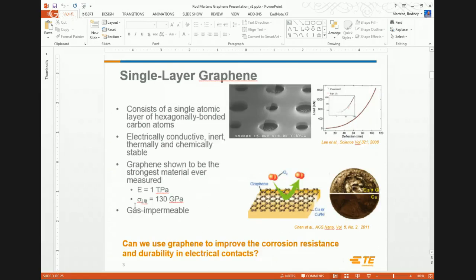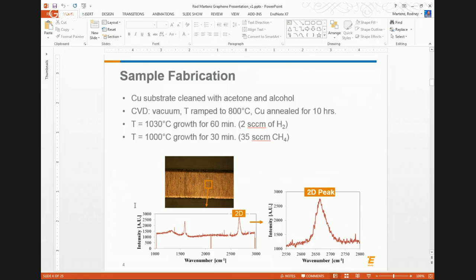So we wanted to actually see if we could grow this stuff on materials that we care about. So we did some sample fabrication at Columbia, and I'll walk through the graphene growth process just a little bit. Typically, the recipe uses pure copper, and then the graphene is CVD, or chemical vapor deposition, deposited at high temperatures. So you can see we're annealing the copper at 800 C for 10 hours, and then we introduce hydrogen at over 1,000 degrees, and then the carbon source is methane for 30 minutes at 1,000.